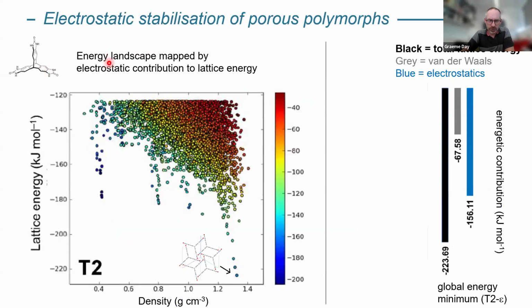So if we look at the landscape of this T2 molecule and all of those predicted structures, here what I'm showing is one of the contributions to the lattice energies of all of those predicted structures. And I've picked out the electrostatic contribution, because remember, part of our design was to put hydrogen bonding groups on these molecules, and hydrogen bonding is largely electrostatic. And what you see is that you have structures here which have weak electrostatics in red. You have structures in green, like the global energy minimum, the close packed structure, which have reasonably good electrostatic interactions for stabilizing that material. And then you have things like these porous ones, and these have this dark blue, a lot of electrostatics going on. And that's why these structures are more stable than they really should be at the density they're at, which is why these sets of structures are dropping down from the landscape in terms of where we are in density.